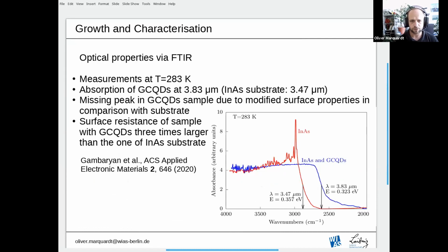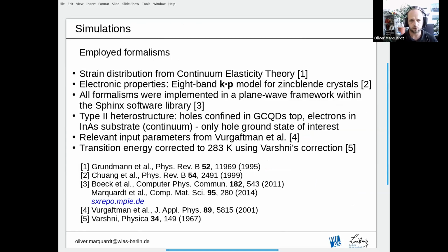We characterize the samples using Fourier transform infrared spectroscopy at almost room temperature. So we have seen the absorption of the graded composition quantum dots at around 3.83 microns. For comparison, the indium arsenide is about 3.47 microns. And we could also see that the surface properties are modified quite a bit by these systems, surface resistance, and you see this peak here in the bulk substrate, which is not there anymore once we have these graded composition quantum dots. So we have then started to do some simulations.